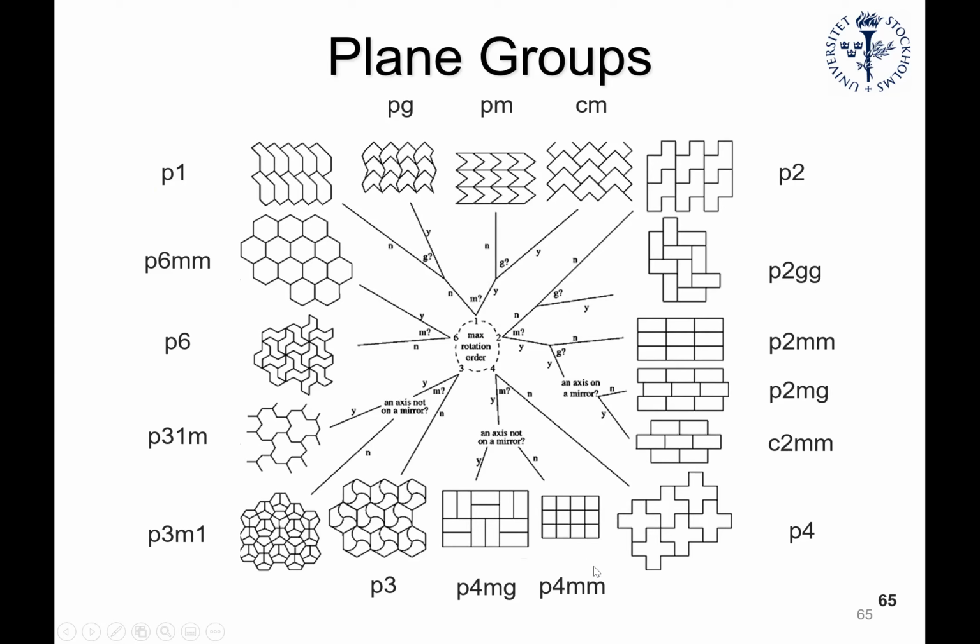So actually the second M is not the vertical or the horizontal mirror plane. It's yet another mirror plane. In this case, we have a mirror plane going along the diagonal as well. So the two diagonals have mirror planes as well. That's why we have two M's here. We have two mirror planes which are not related by any form of symmetry, two unique mirror planes.